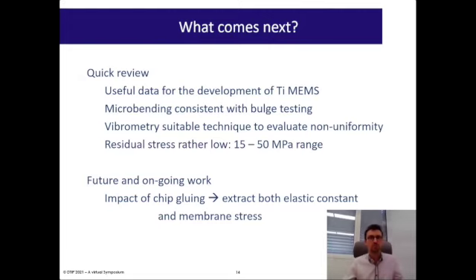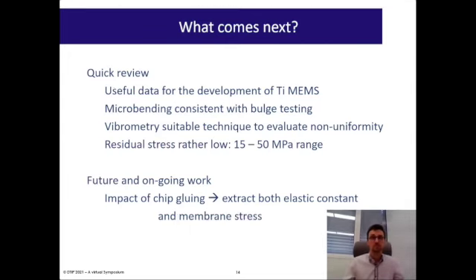Let's now have a quick summary. We presented useful data for the development of thin membranes, such as pressure sensors or microvalves, used in harsh conditions. We obtained microbending results which are consistent with bulge testing results. Vibrometry was used and seems to be a suitable technique to evaluate the non-uniformity of the membrane. Using these techniques, we were able to estimate the effective residual stress in the range of 15 to 50 megapascal, which is quite low for this kind of membrane. Future work will be more focused on the impact of chip gluing to extract both elastic constants and membrane stresses.